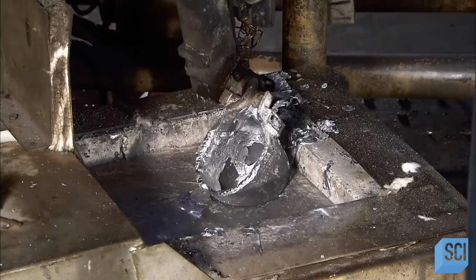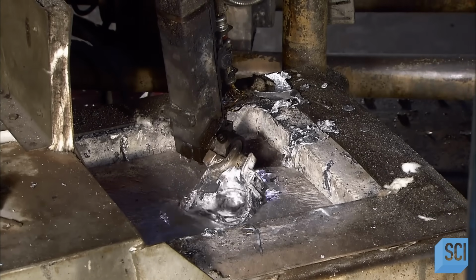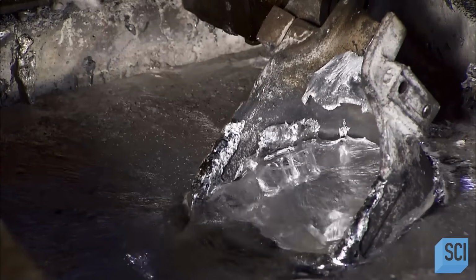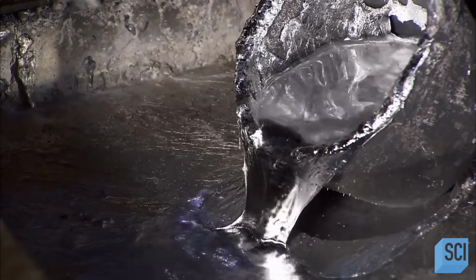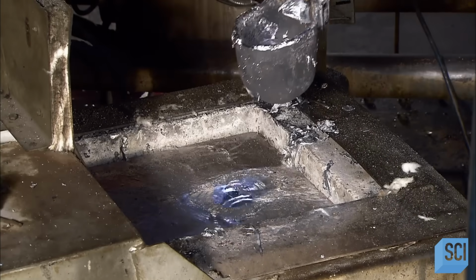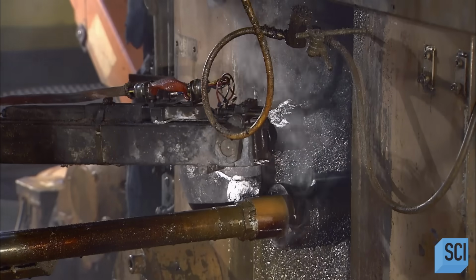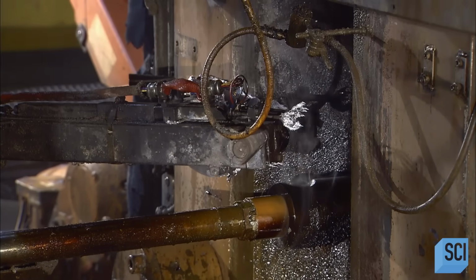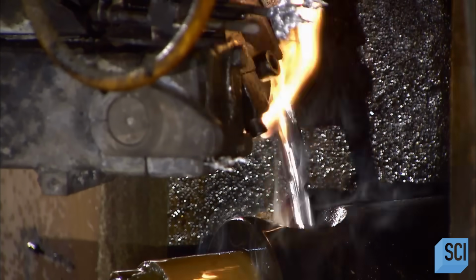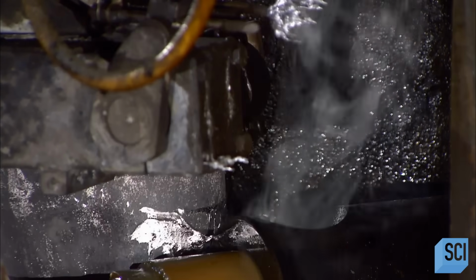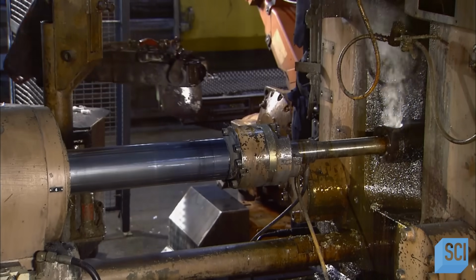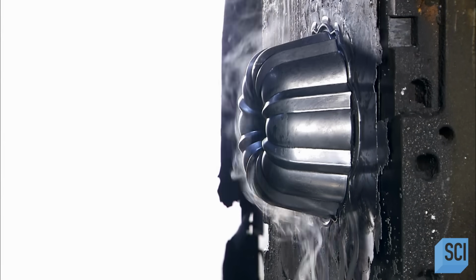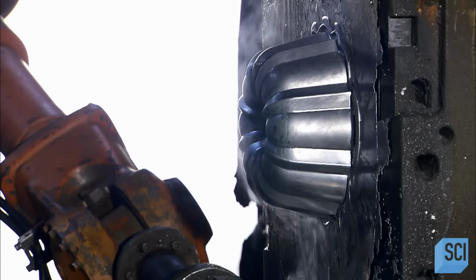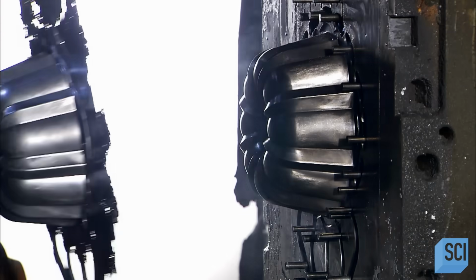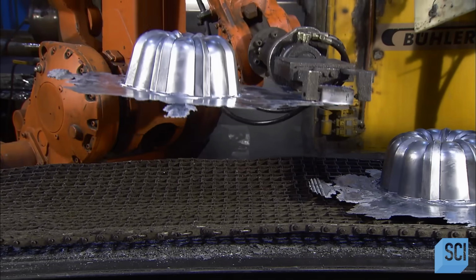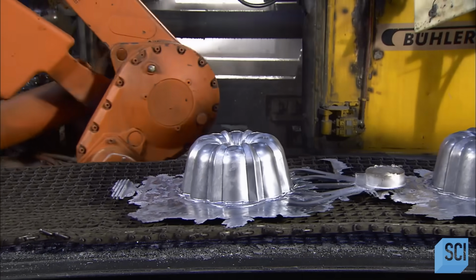The casting process is entirely automated. A ladle descends into the holding furnace and scoops up just under 1 kilogram of aluminum, enough to make 1 Bundt pan. The ladle then pours the molten metal into a sleeve, which a high-speed ram immediately pushes into a steel Bundt pan mold. The pressure and speed combined shoot the molten aluminum into every nook and cranny of the mold cavity. As the hot aluminum hits the cooler mold, it solidifies in about 10 seconds. Then the two halves of the mold automatically separate, and a robotic arm extracts the cast pan.